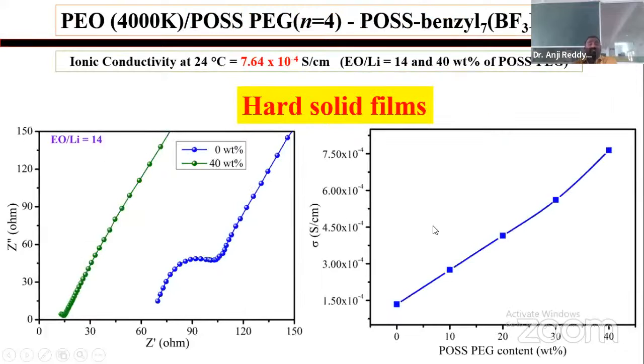This is after adding POSS-PEG. Without POSS-PEG, we achieved the order of 10 to the minus 4, that is 1 point something, at 24 degrees. After adding POSS-PEG, the conductivity increases more, to 7.64 times 10 to the power of minus 4, at EO to Li ratio 14, at 24 degrees or so. These are the impedance plots, four plots.